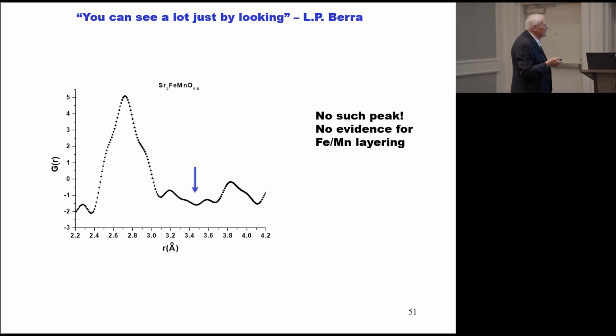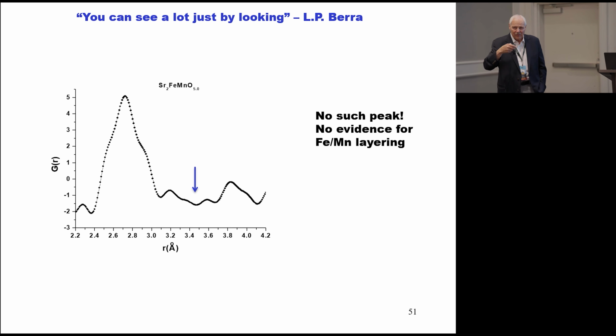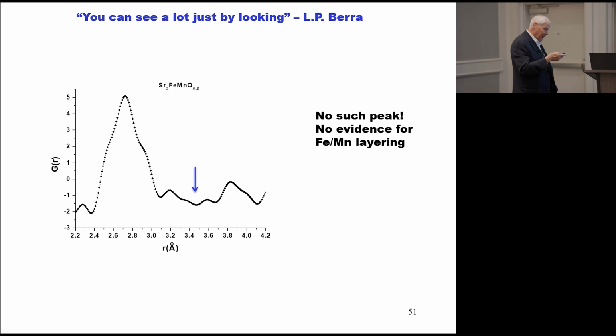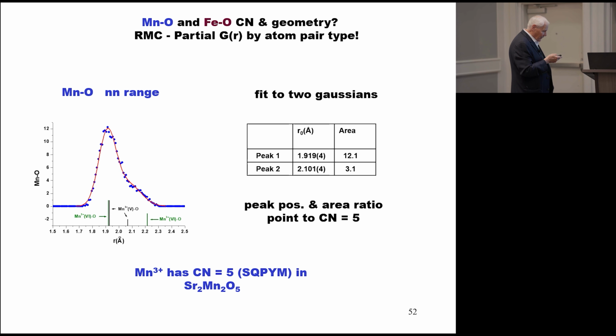Here's 3.4 angstroms. There's nothing there in the G of R, and there's something at 3.8. So you get a result that is completely opposite to what you would predict if you had anything resembling a Brownmillerite. Okay, let's look at the local environment peak.